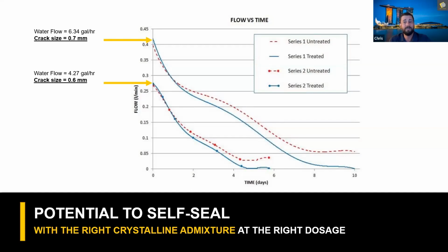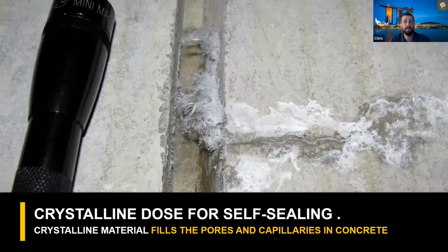So this testing not only shows that the treated concrete stopped the flow of water through the crack, but also that this particular crystalline product self-sealed cracks of 0.6 and 0.7 millimeters while stopping a water flow of over 152 gallons per day. So to be confident in a product's self-sealing ability, specifiers should look for an admixture and a dosage level with independent testing guaranteed to self-seal cracks of at least 0.5 millimeters.